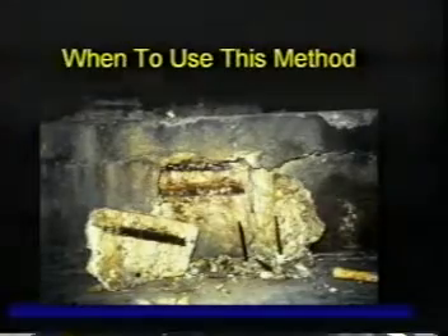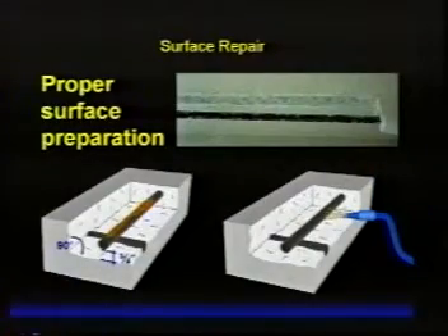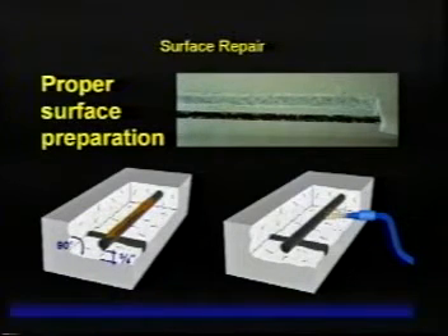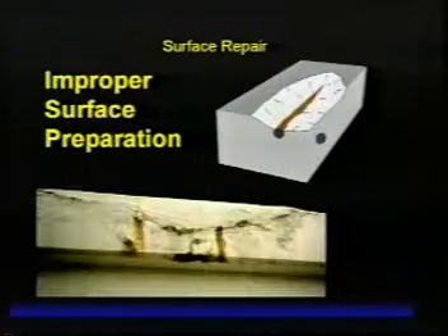When do we use these methods? These RAP documents are really designed primarily around repair of spalled concrete due to corrosion of reinforcing steel. So anytime we have any vertical or overhead concrete that has this type of defect, these methods are appropriate. The surface preparation follows the ACI guideline, which is preparing around affected bars, removing concrete, clearing about 3/4 of an inch, squaring up the shoulders.